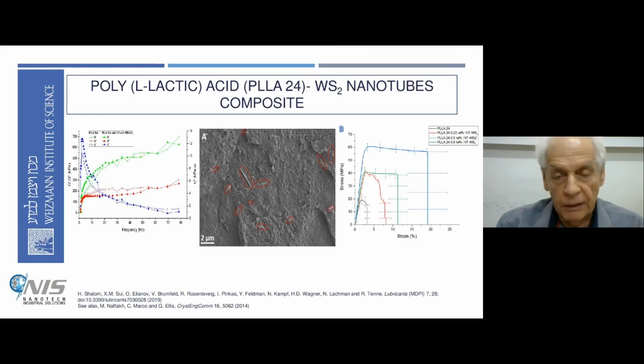One example is these nanotubes, which we impregnated into polylactic acid. Polylactic acid is one of the main biocomposite polymers used nowadays in medical procedures and many other applications, including food packaging. We add very little—0.25, 0.5, even up to 0.8 percent—though usually 0.25 to 0.5 is the optimum.